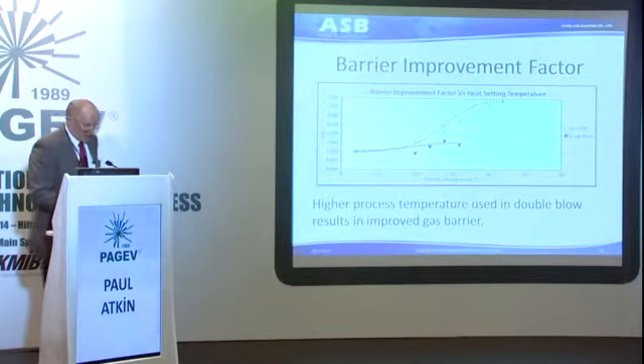This is just some data that supports that. We see the single blow here creates a very modest increase in gas barrier, but the double blow brings us right up to about 1.3.